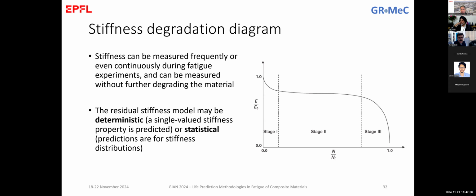You can imagine structures that have rotating parts. Imagine a wind turbine rotor blade that rotates, and due to the damage, the stiffness is reduced, so the blade becomes more flexible. At a certain point, the stiffness reduces so much that the blade hits the tower. So this is, of course, not acceptable. So there, instead of talking about failure criteria that are constrained only to strength values, so that the material does not fail, we might also assign performance criteria, in this case criteria based on stiffness, that can say, for example, that if the stiffness drops more than 10%, then we assume that the material has failed.